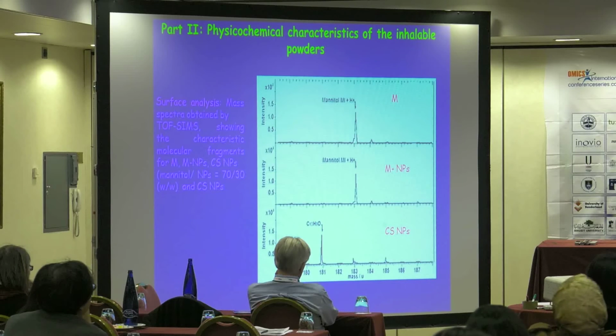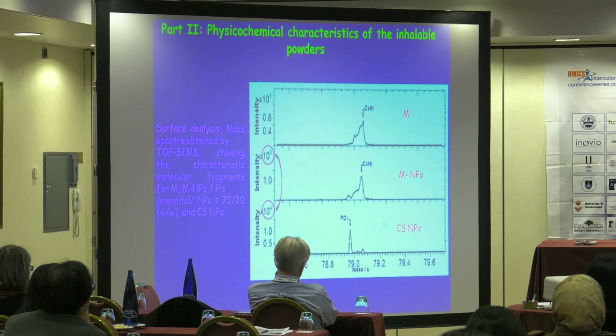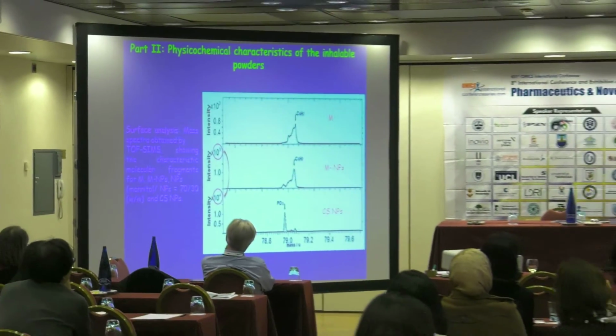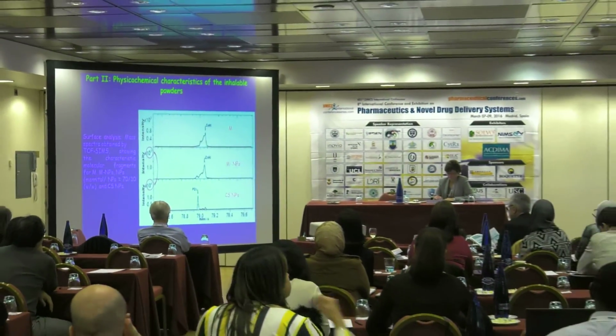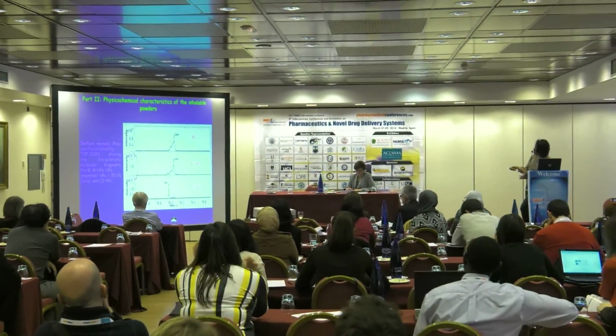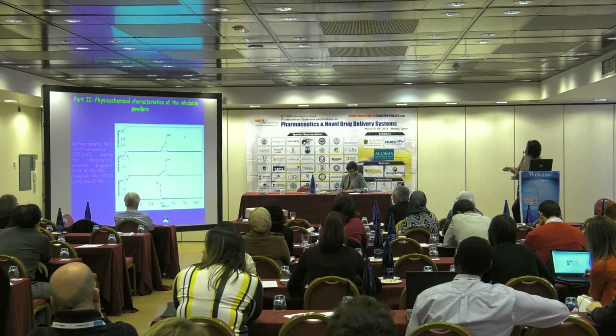However, we detected another fragment signal that was not present in the powder spectra. Screening in another region, in the spectra of chitosan nanoparticles we could detect PO3, attributed to the cross-linker used in the nanoparticles, which was not detected in the spectra of the powder formulations.